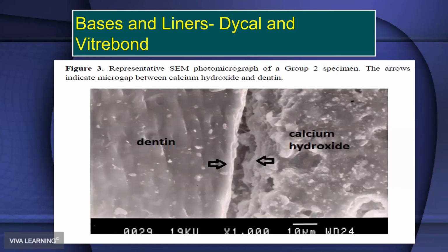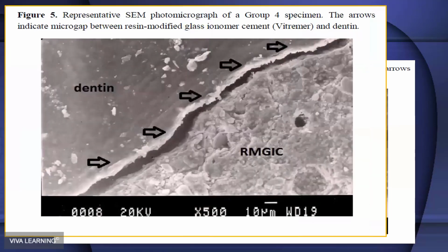Now, you could get by with it, like I mentioned before, with a casting, because it goes right on top of it, or amalgam that you're packing down, because you're packing down the calcium hydroxide at the same time. But when you do a composite and you cure the composite, it's going to shrink. It's going to pull the Dycal away from the dentin. And the shrinking is enough to actually pull the resin modified glass ionomer off too. Resin modified glass ionomers like Vitrebond only have a bond strength to dentin of about 7 to 9 megapascals, and the polymerization shrinkage can be 12. So if you have a deep preparation, you're going to end up with a gap that's going to pull away.